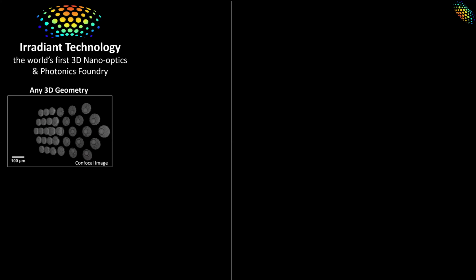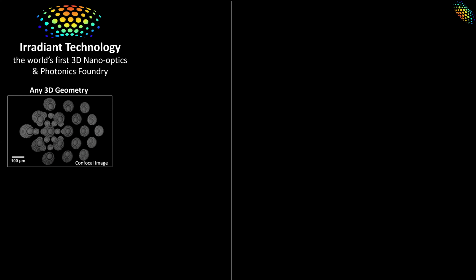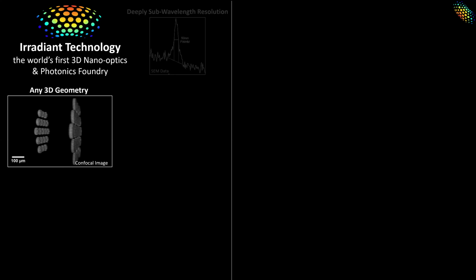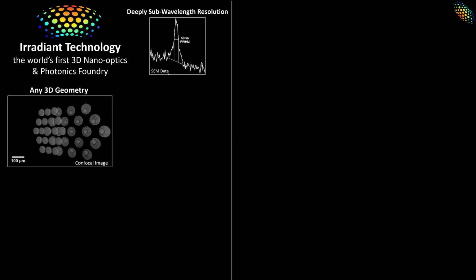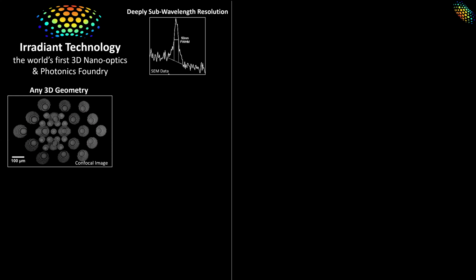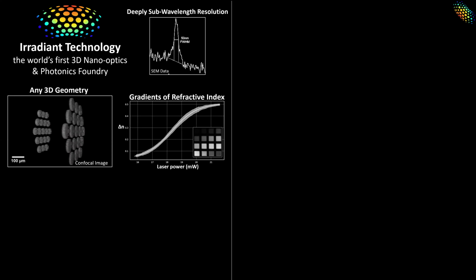And so this is what we're doing here at Irradiant, making what we call the world's first 3D nano optics and photonics foundry. We can fabricate any possible 3D geometry. It doesn't need to be self-supporting or contiguous. We can do it with deeply sub-wavelength resolution, down to tens of nanometers if necessary. But in a lot of cases, we found actually a few hundred nanometers is a lot easier and perfectly sufficient because we can directly pattern gradients of refractive index. And we can do this with an index contrast from less than 0.1 up to above 0.5. So an index contrast comparable to the contrast between glass and air.